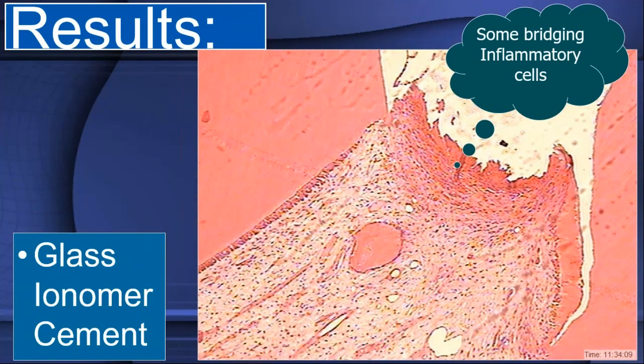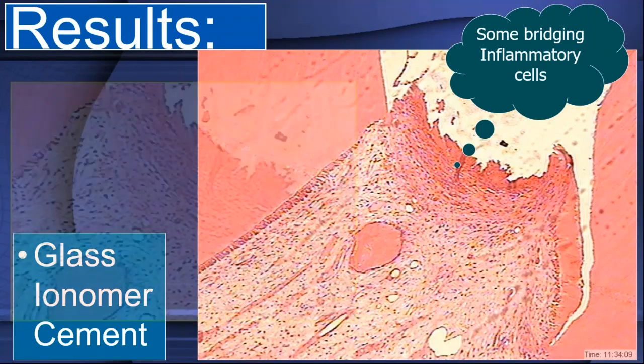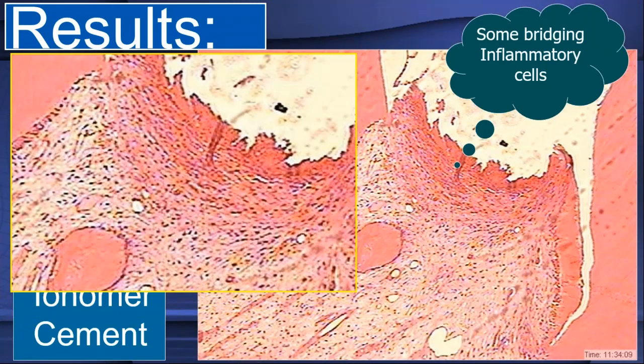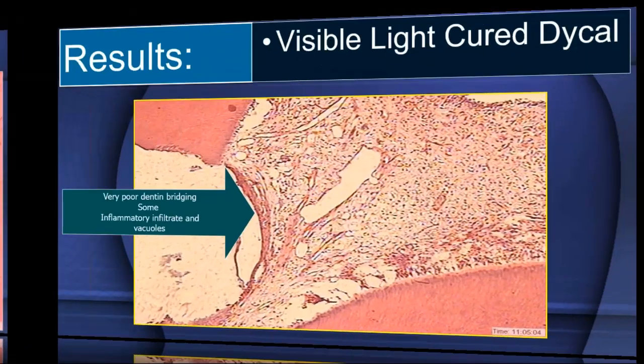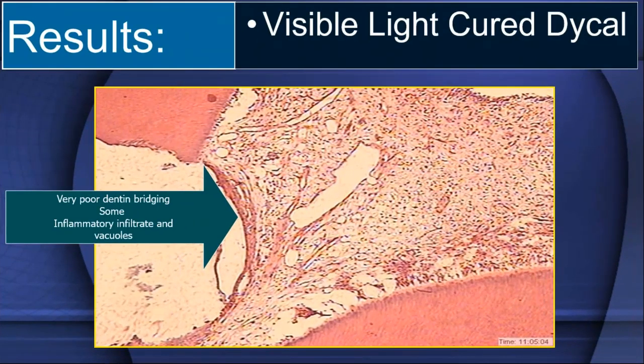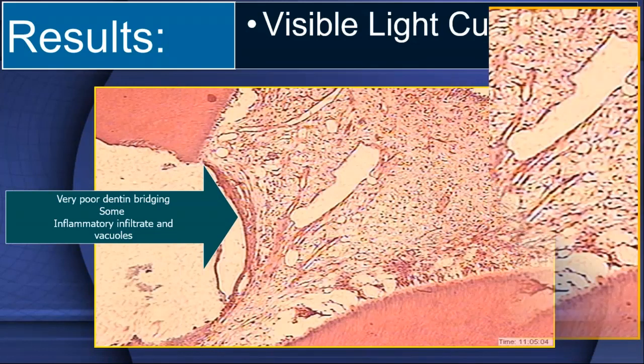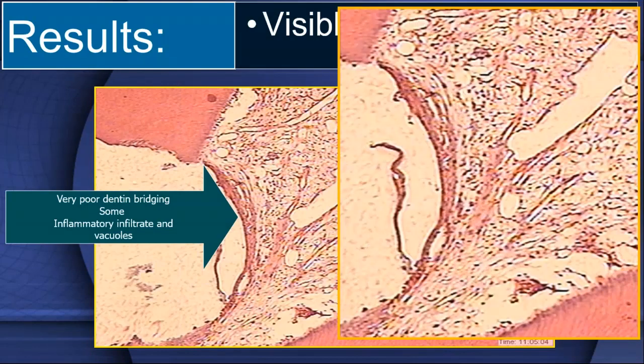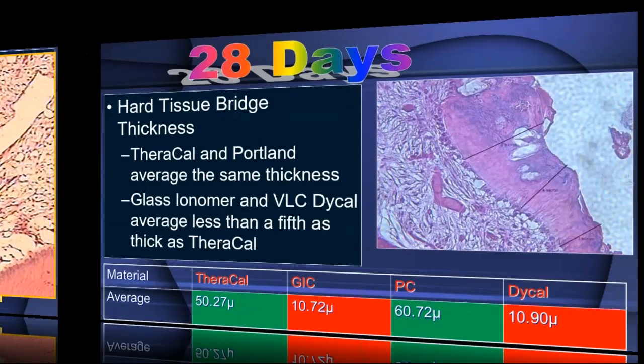Glass ionomers did as we thought they would. Again, lots of inflammation, vacuoles, some scar tissue, very poor bridge formation, just a lot of scar tissue forming there. VLC Dycal also, some poor dentin bridge formation. Again, not enough calcium, not alkaline enough to be a good pulp capping agent. That's why it's really not indicated for that. Some inflammatory vacuoles and infiltrate. And these are pretty representative slides of the whole thing.